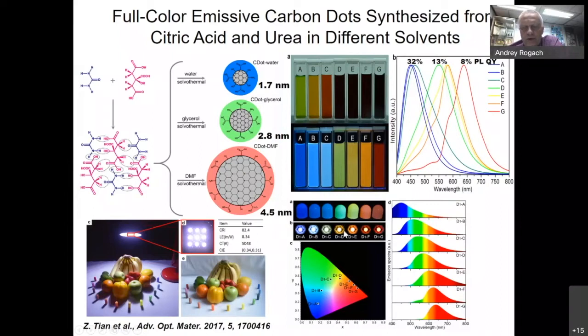And we can also make so-called down conversion LEDs out of these materials, which is shown here on the bottom row. And this is a good example of use for these materials for LED. So this can be used as a lamp, right? So different color tiny lamps. Or when we combine blue, green, and red color together, we can make LED which emit white light. And this is already a real life application because we can use them for lighting. We can make lamps out of these LEDs, and these lamps will provide us illumination of, for example, this kind of fruits here with a high quality white light.